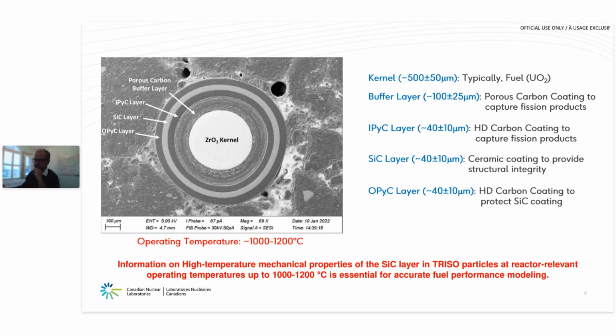the fuel kernel itself. The next to it, the third layer that you see, which is a darker layer, is a high density carbon coating. It's called inner pyrolytic carbon coating, which is about 40 plus minus 10 microns in thickness. And the idea is that, whatever fission products are not captured in buffer layer will be captured by this high density carbon coating.